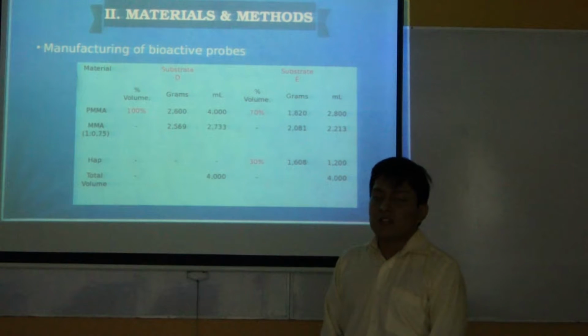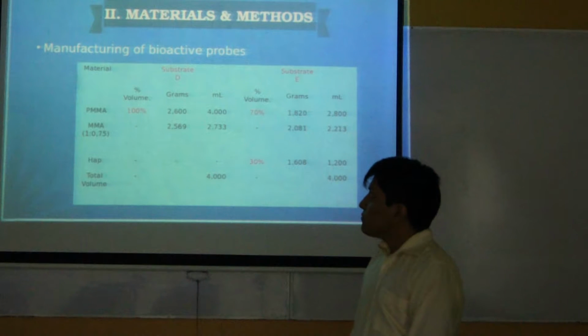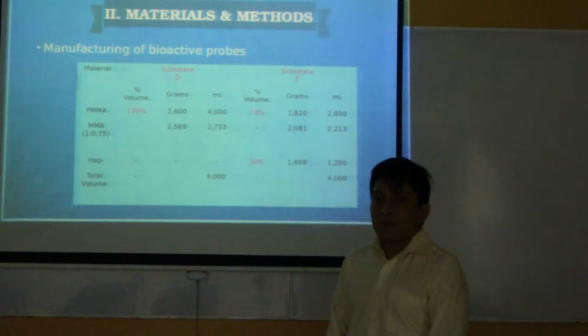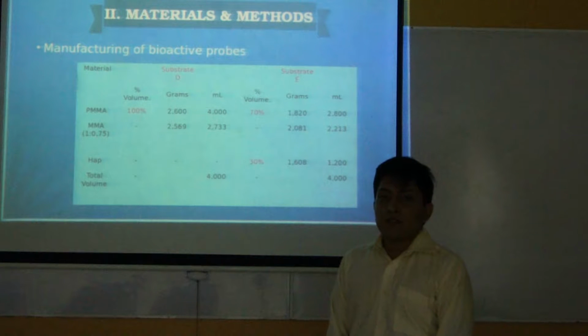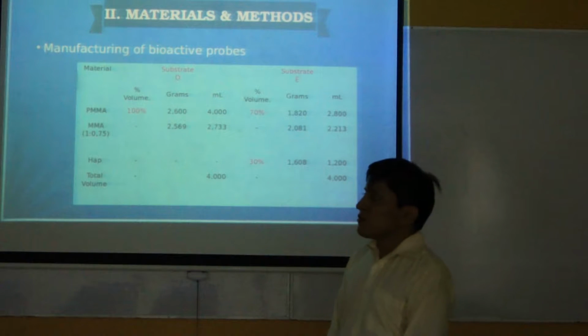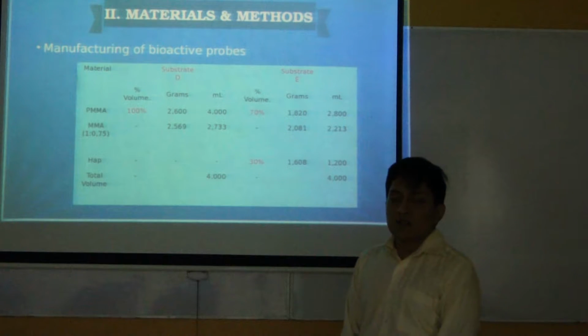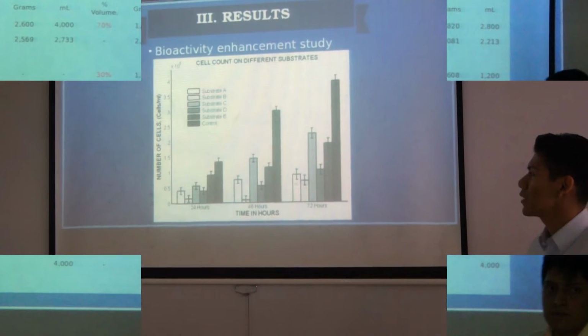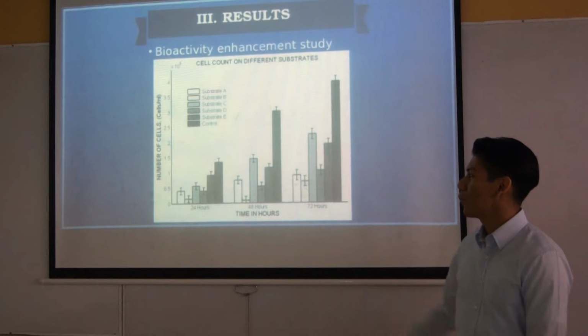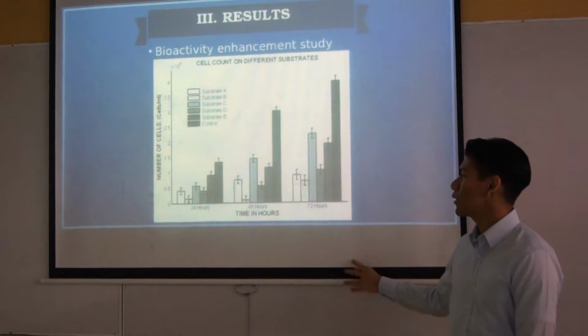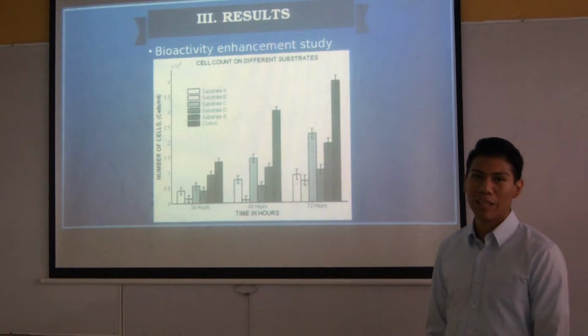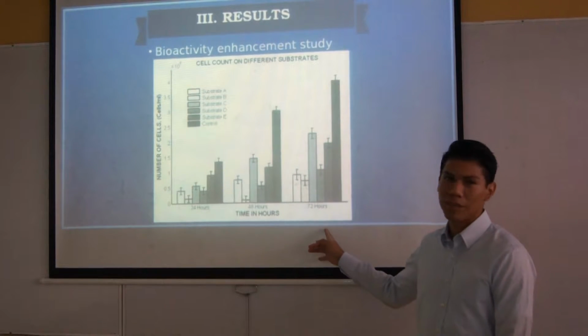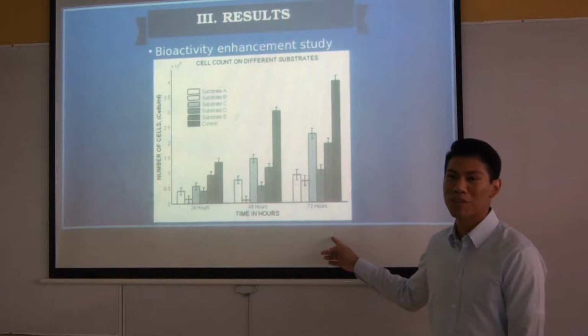Here we have the second chart with the last 2 compositions. The first one contains 100% polymethylmethacrylate, and the second one contains only 70% with 30% hydroxyapatite. As we can see in this graph, we have 2 axes, and we counted the number of cells per milliliter in each substrate for each day in intervals of 24 hours.